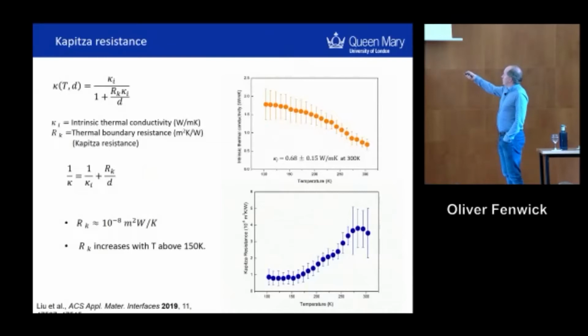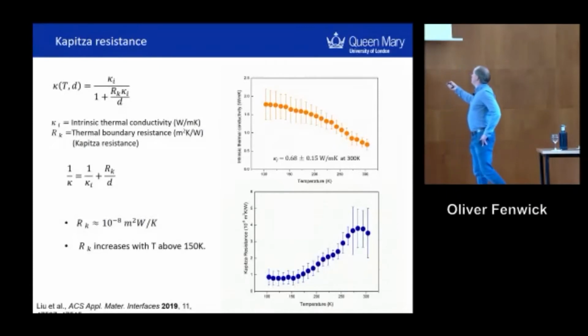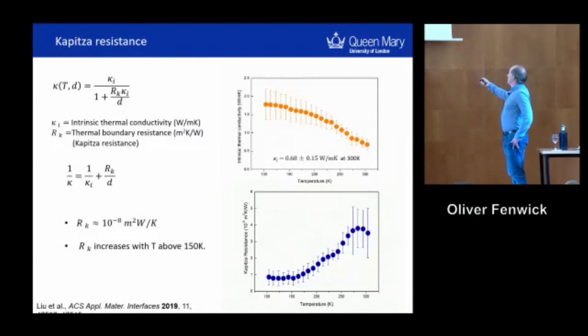This thermal boundary resistance is Rk in this formula. You've got your intrinsic thermal conductivity of the material under test. You've got the characteristic grain size or domain size, and then that's your measured thermal conductivity on the left. Rearrange that, and you can see if you plot 1 over your measured thermal conductivity against 1 over the dimension of the grain, you can extract, hopefully, the thermal boundary resistance and the intrinsic thermal conductivity, which is what we've done, with some reasonable error bars. So we find our intrinsic thermal conductivity, of course, is slightly larger, closer to 0.7 watts per meter Kelvin at room temperature.